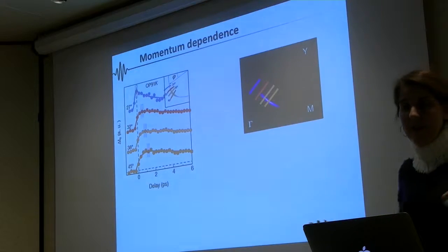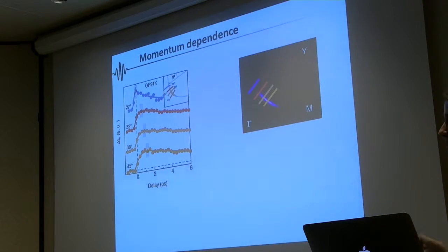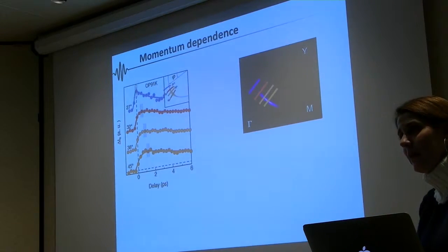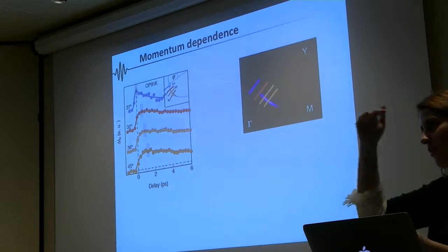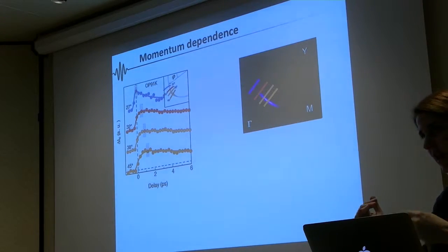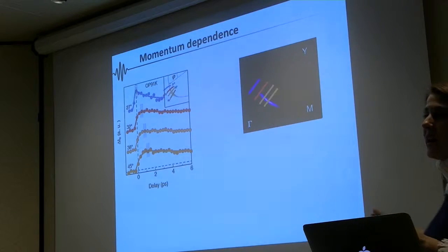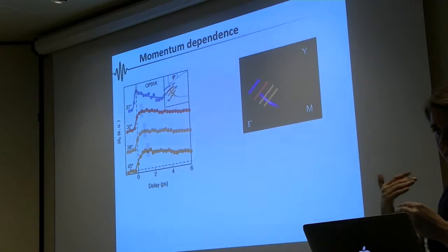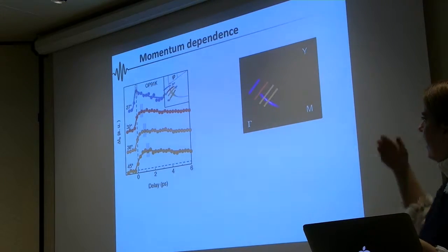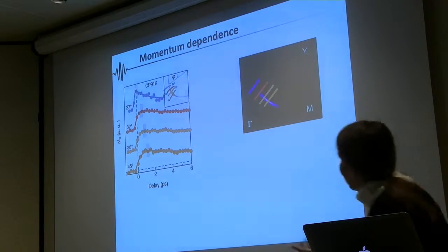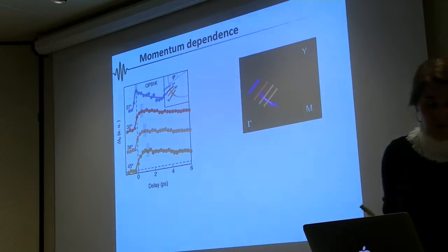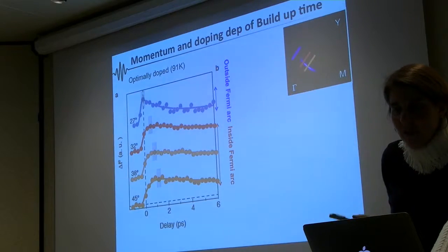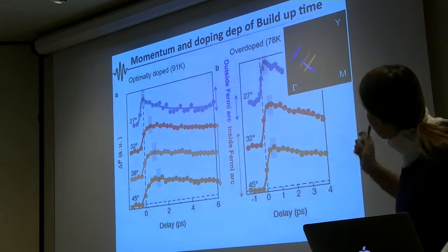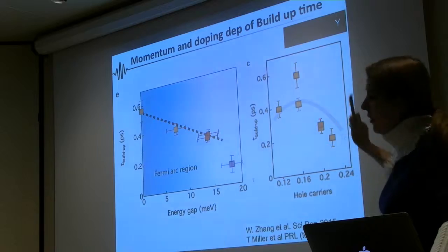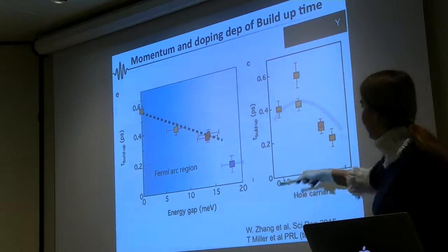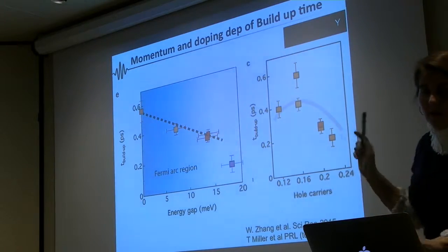So this build-up time is obviously related to the superconducting gap, because I showed you that if I add energy above, there is no delay time. If I completely kill all the superconducting pairs, there is no build-up time. I showed all this. The only remaining point is this. This is for another sample, but we see the same thing for all different doping. There is some doping independence of this build-up time, but this is beyond the scope here.